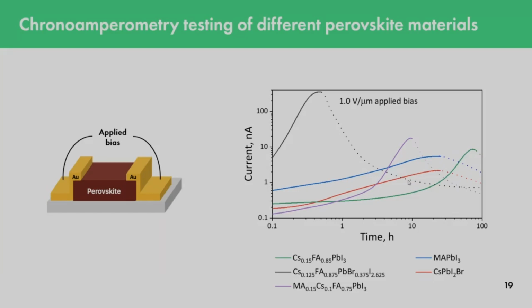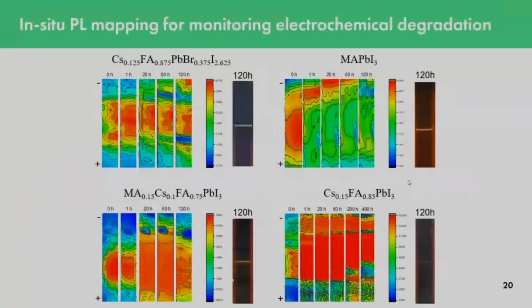And according to this assumption, the most promising material out of these 5 is the first one, cesium formamidinium lead iodide. And the worst one is fully inorganic cesium lead iodine bromine. PL mapping also confirmed our suggestion.